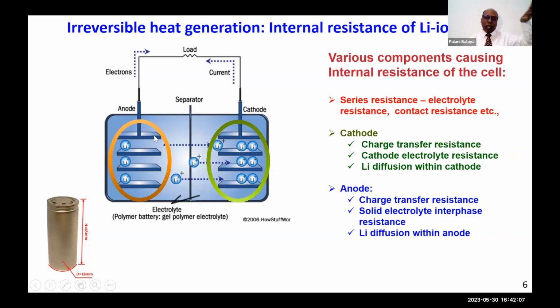Or what is happening on the anode, that is, again, you have charge transfer resistance. Lithium ion is extracted and the electrons are extracted. Both of them have to be extracted efficiently. If there is any resistance, that would give rise to internal resistance. Or the SEI I mentioned to you, the graphite in contact with the electrolyte, giving rise to a thin polymer layer, that can give rise to it. The last one is the chemical lithium, that is, the lithium ion and the electron diffusion within the graphite.